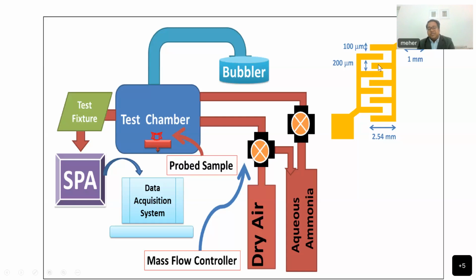So the nanomaterial was deposited on this, and the electrodes were put here, and we measured the electrical properties, I should say resistance especially, of the device. And this is dry air, this is aqueous ammonia, and this bubbler, this is the test chamber. So the ammonia goes from here, and these are the mass flow controllers. Mass flow controllers basically control the flow of the gas.